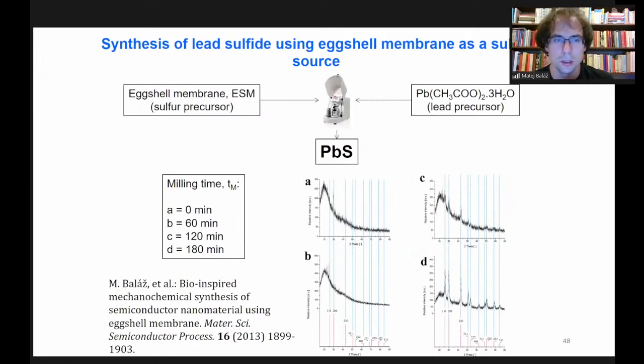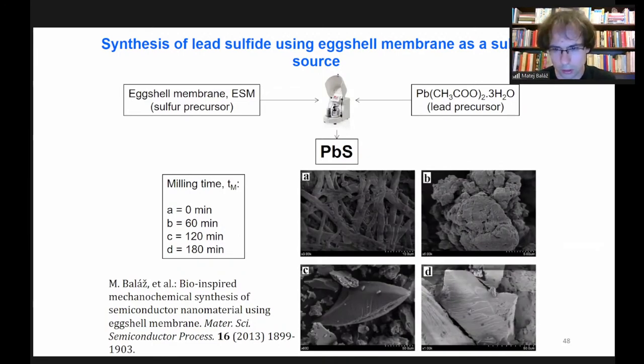Another interesting application is to use eggshell membrane as a source of sulfur, because as I mentioned, it's a proteinaceous structure composed of amino acids, and there are a couple of sulfur-containing amino acids like cysteine, for example, and the content of sulfur in eggshell membrane is about 2 or 3%. In our experiment, we just milled eggshell membrane with lead acetate, which was used as a lead precursor, and we were able to prepare lead sulfide. In about 3 hours, we started to observe the peaks corresponding to galena, lead sulfide, in the XRD patterns, and the particles look like this. In our paper we call them fish-like particles, because they remind one of fish a little bit. Of course, this was a composite of lead sulfide and the residual organic matrix.